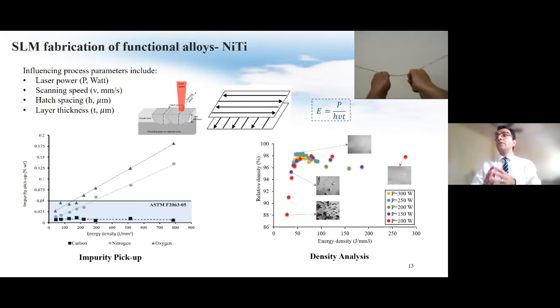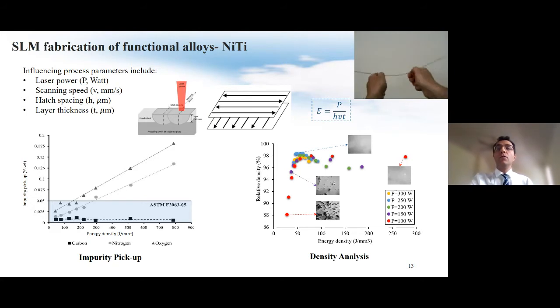Now I would like to talk about the procedure of processing parameters optimization that we perform in our lab for a very interesting material called nitinol or NiTi, shape memory alloy. The term SMA or shape memory alloy might be familiar to you. As you can see in this video, on the top right, SMA can undergo a significant amount of strain, up to 8%. Just for your information, stainless steel is about 1.5%. And it can be deformed before it enters the plastic region. That is why we call this material superelastic alloy as well.